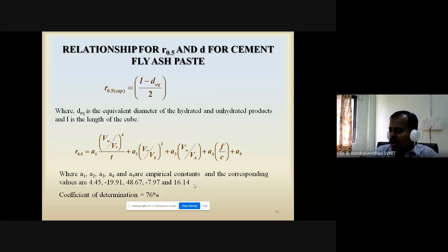Then how to do the modeling of the R.5 in case of cement fly ash system? Because the packing of cement and fly ash is not known to us, it is nowhere available, so it is not so easy to do the modeling. Then what we have done: we consider hydrated products of cement and fly ash and unhydrated products of cement and fly ash are stacked together and make a sphere inside the cube. That's what we assume, and we calculated the equivalent diameter. Actually here we are using the equivalent diameter of the sphere. That's how we calculated the R.5 capillary entry radius.